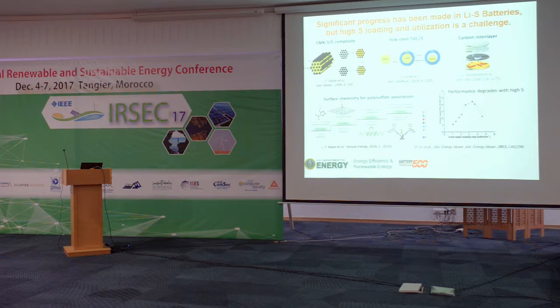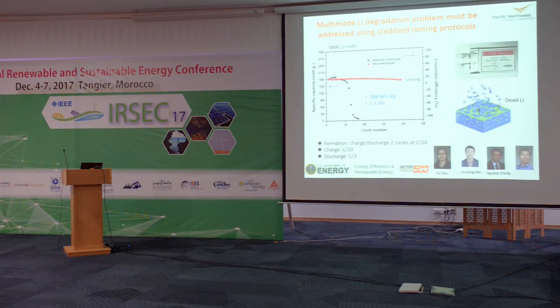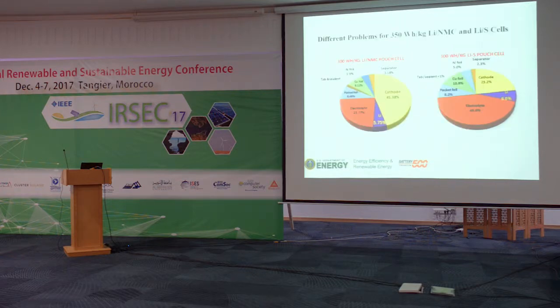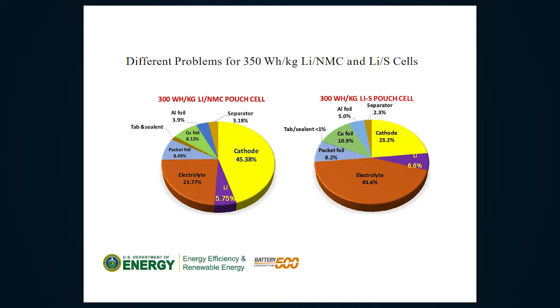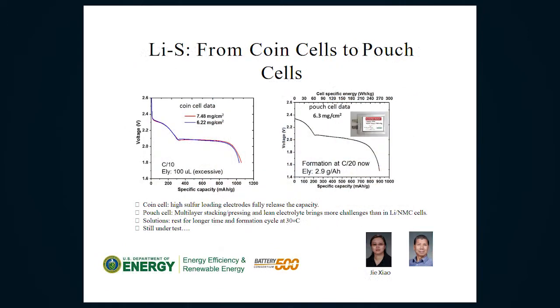If you compare the Li/NMC cells with the sulfur cells, look at the cathode material, just half of the weight. But if you use nanostructured carbon, the high porosity and high surface area mean you use a lot of electrolyte. The amount of electrolyte is more than half of the cell. So if you do this, certainly it will be very, very difficult. We really need to find ways to increase the sulfur loading and reduce the amount of electrolyte in the lithium sulfur system. Again, showing you this, if you don't restrict the conditions, things work very nicely.